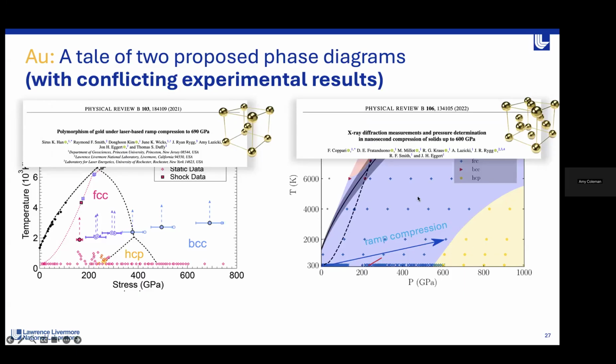On the right-hand side here is the same prediction of a phase diagram, but what I want to highlight is this ramp compression blue arrow. This represents a series of ramp compression experiments conducted by Federica Coppari, where they saw up to about 600 GPa, there was no transition to BCC phase in gold. So just FCC all the way up to 600 under ramp compression.